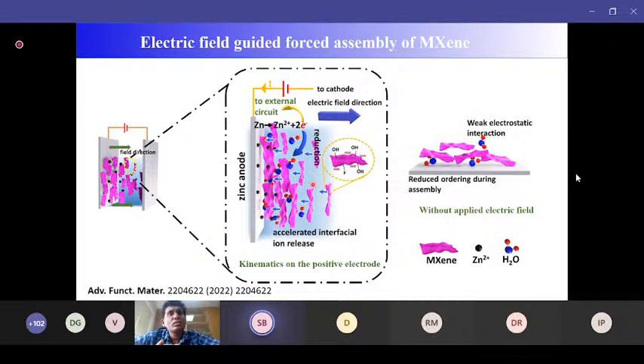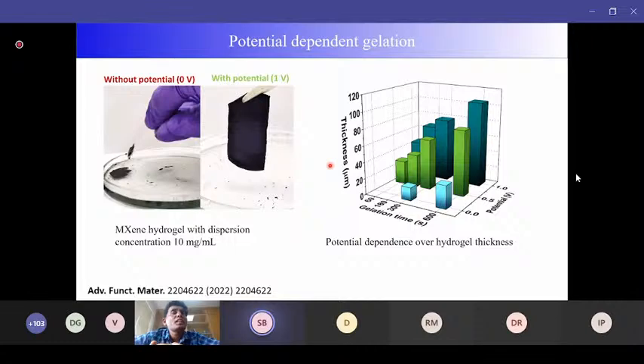So it leads to the oriented hydrogel, and we can get the hydrogel with like this. This is the potential. With the 1 volt potential, we can get a freestanding structure. Without potential it is completely brittle.